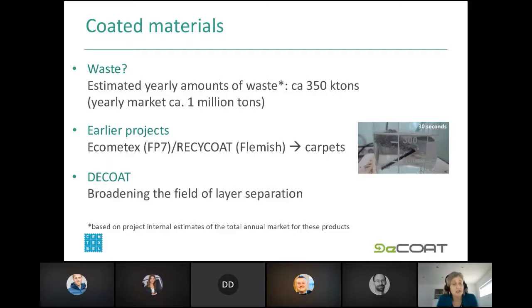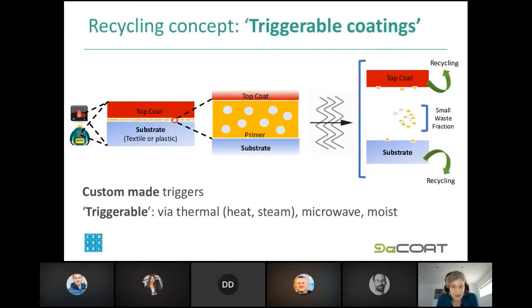So the European FP7 project Ecometex and a Flemish project Recycoat both looked at how to debond different layers in carpets. Here you see a picture where, for example, a carpet is put in boiling water, and after 30 seconds, you can see that the bitumen backing nicely separates from the piles. And this is done by adding additives into the coating layer. And within DECOAT, we want to broaden the field of layer separation, so not only looking at carpets, but at all kinds of other textile products. You have seen this passing by already in Guy's presentation, so I will not go into too much detail on this. I will focus next on the custom-made triggers we will put in the primer layer, which will be triggered via heat or steam, microwave or moisture.